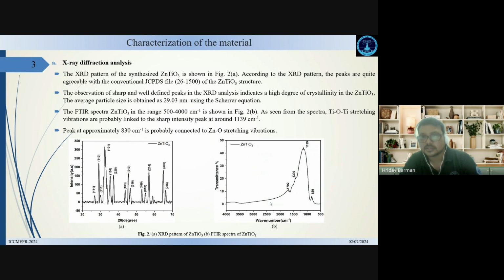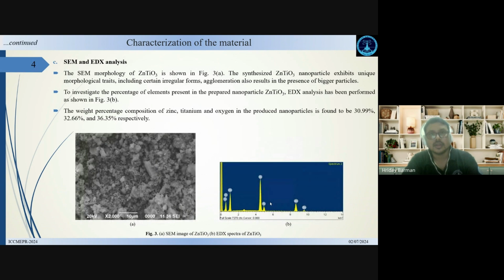From this, it is clearly seen that Ti-O-Ti stretching vibrations are probably linked to the intensity peak of 1139 per cm, and approximately 830 per cm is probably connected to the zinc oxide stretching vibrations. Also, SEM and EDX analysis has been done. As we can see in figure 3a, the SEM analysis shows unique morphological traits, including certain irregular forms, which are agglomerated in the presence of bigger particles. To investigate the percentage of elements present in the prepared nanoparticle, EDX has also been done, and we found that 30.99% zinc, 32.66% titanium, and 36.35% oxygen is present.